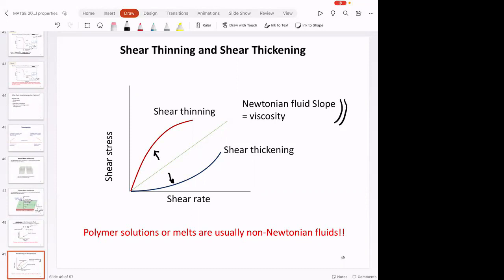There are lots of cool behaviors of non-Newtonian fluids, but in essence, we have shear thickening fluids. You see that the stress goes up as shear rate increases. So the derivative of this curve is higher here than here. So the dynamic viscosity is increasing as we shear it more. The material is getting thicker. Things with higher viscosity, we say, are thicker as we shear it more. And that's the opposite of shear thinning. You see the derivative here is less than the derivative here, and so the material is getting less viscous as we shear it more.